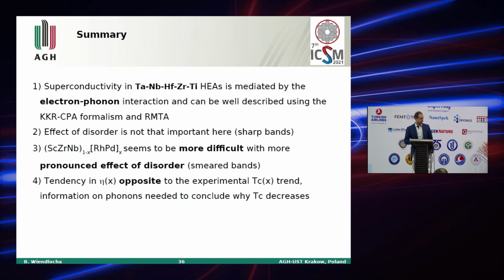And with this, I would like to come to the summary. So I presented you two examples of high entropy alloys. The first alloy, superconductivity in this first alloy is for sure mediated by the electron-phonon interaction. So the effect of disorder is not that important here. And the second alloy seems to be more interesting, more difficult, and our initial results show that we have the opposite tendency in the change of McMillan-Hopfield parameters with concentration of atoms than TC suggested from experiment. So thank you for your attention.